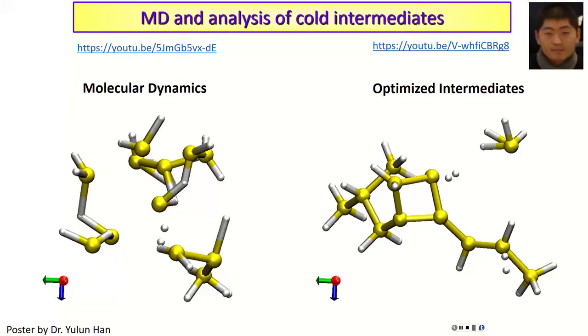So through these relaxed intermediates, it shows formation of, like, it's not quantum dots, but clusters with multiple three and even four coordinated silicons. Well, in the original precursor, they all are two coordinated. Right? Each silicon has only two silicon neighbors, right?